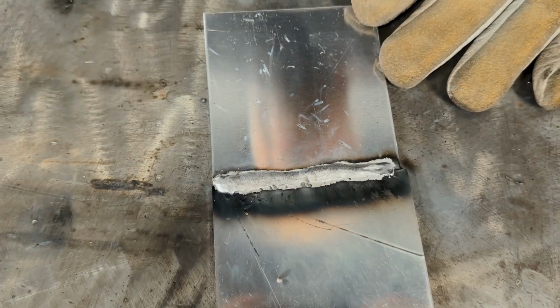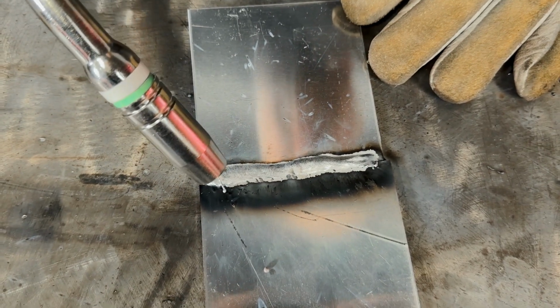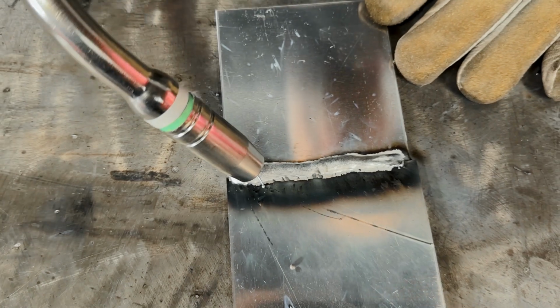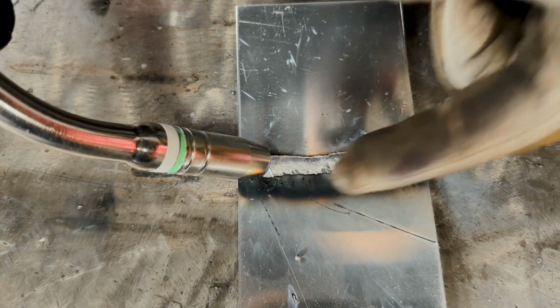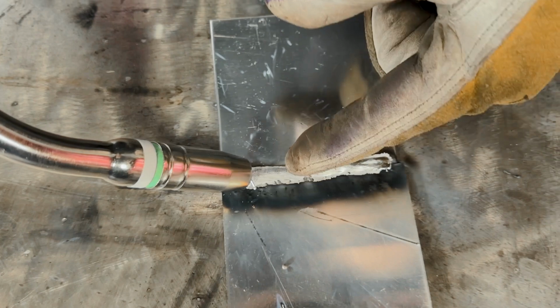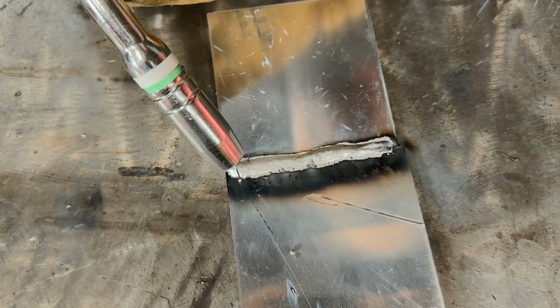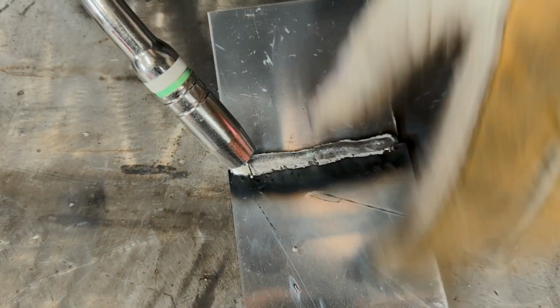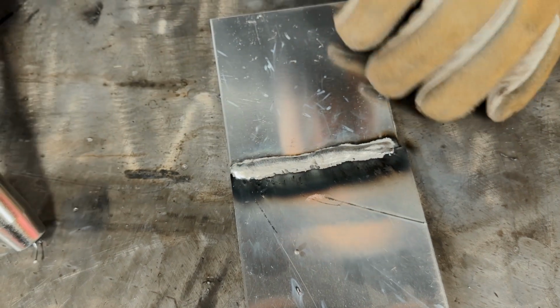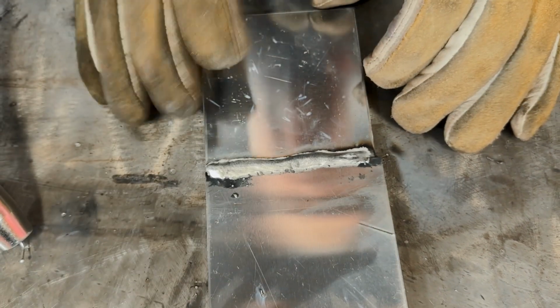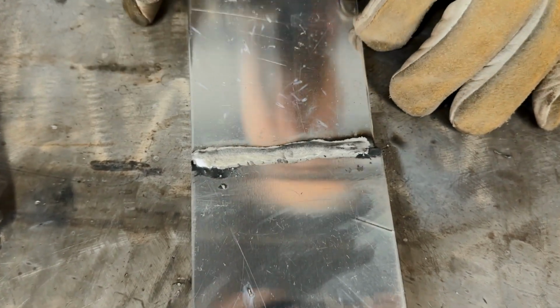So by the soot, you can see my gun angle was not perfect. If my gun angle would have been perfect and the gun would have been up a little bit more, we should have had equal soot on both sides and a little bit less. I had a little bit shallow of an angle here, so the soot is only on the back side, not on the front side. Little bit of peppering in there, not too bad. That is because we did not clean any oxides off or prep anything.